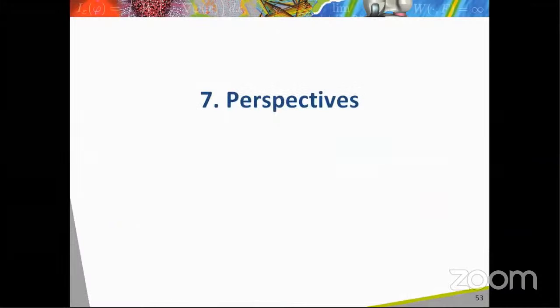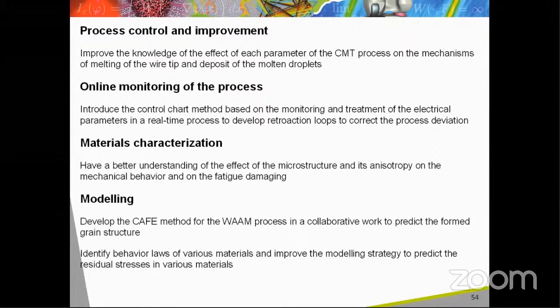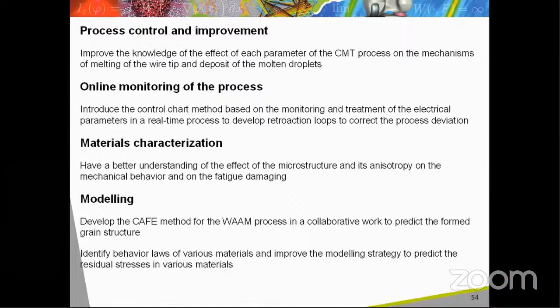In the field of the process control and improvement, we have still to improve the knowledge of the effect of each parameter of the CMT process on the mechanism of melting of the wire tip and on the deposit of the molten droplets. Concerning the online monitoring of the process, one can consider to introduce the control chart method based on the monitoring and treatment of the electrical parameters in real time to develop a retroaction loop and to correct the process deviation.